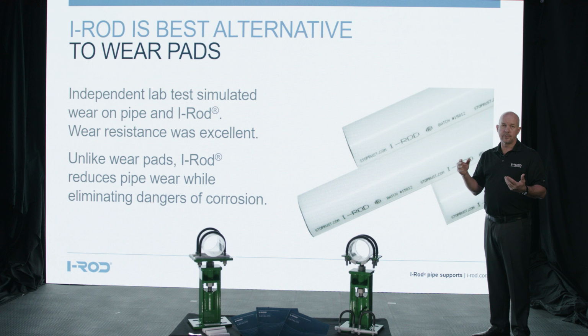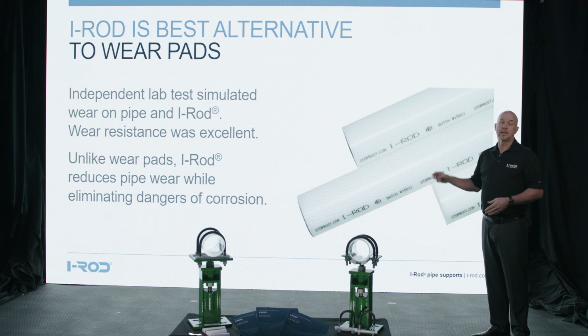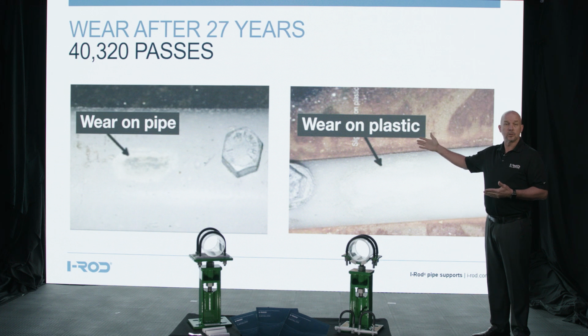One of those FRP companies that sells the FRP pads purchased some I-rod from us unknowingly. They were trying to prove that FRP pads were better for wear resistance than I-rod. So they purchased a piece, hired a third-party laboratory, and had a 2-inch steel pipe that was moving back and forth something like 5,760 times per day. Then they published the evidence from that report, and we saw that online, and we captured it.